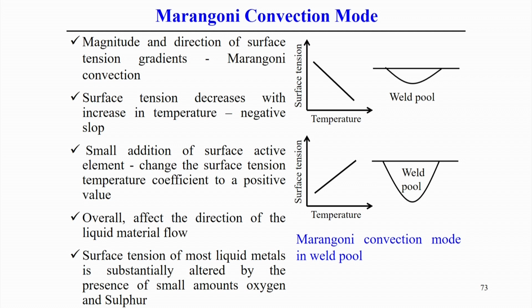The magnitude and the direction of the surface tension gradient influence the material flow within the weld pool. In a single term, the material flow within the weld pool is called the Marangoni convection. So, normally, in the Marangoni convection mode, if you see the first figure, surface tension actually decreases with increase in temperature.